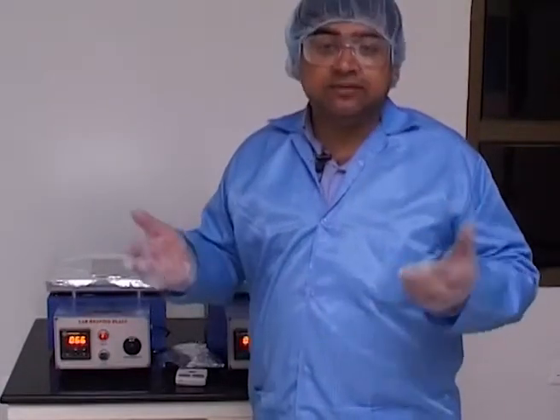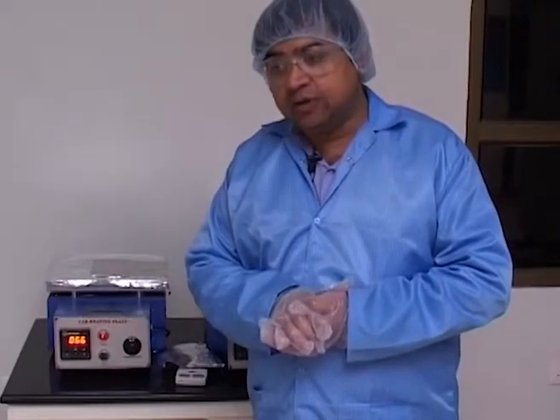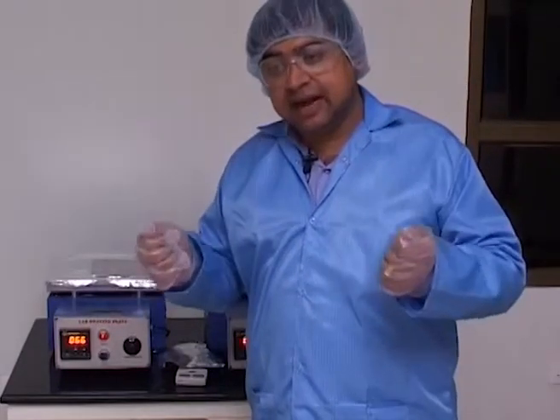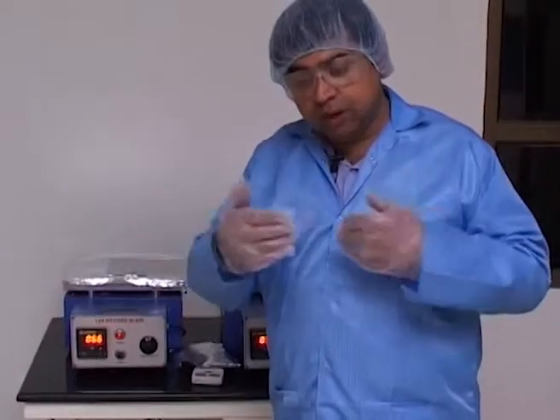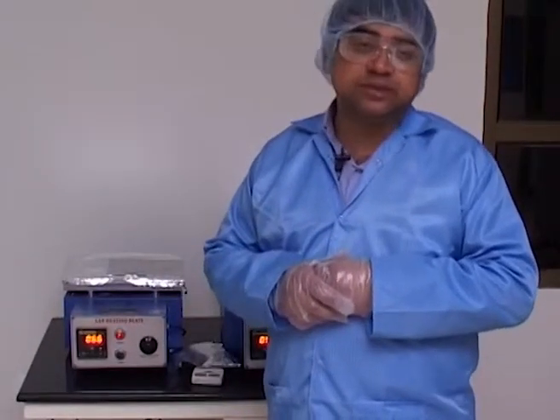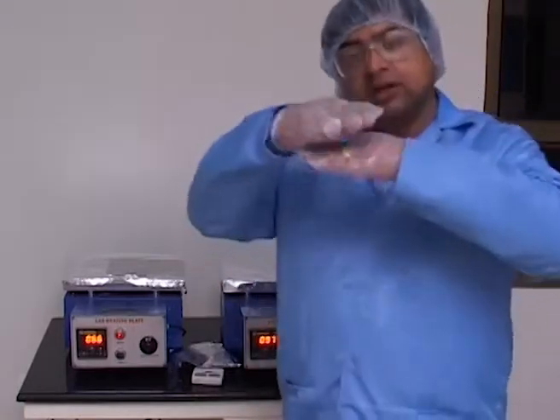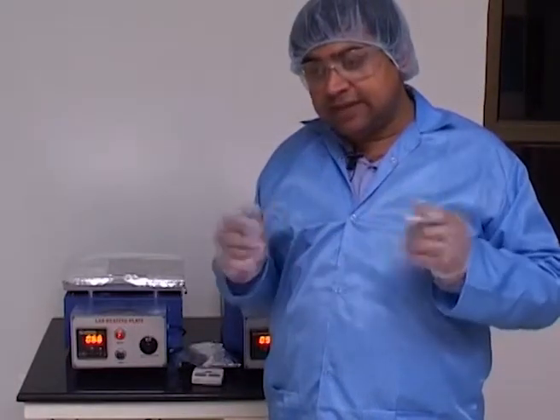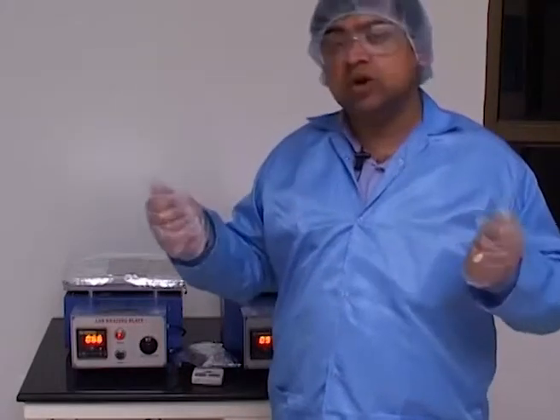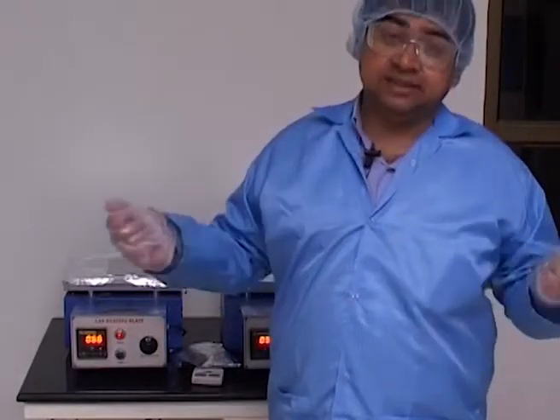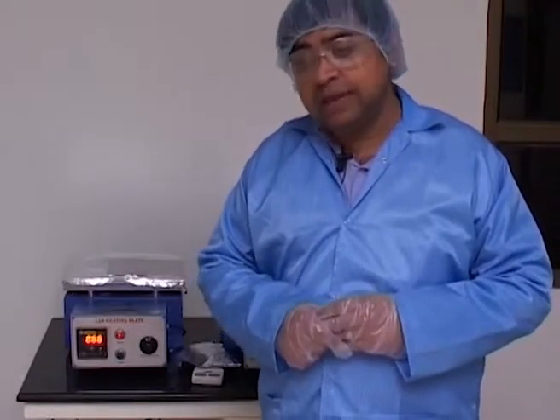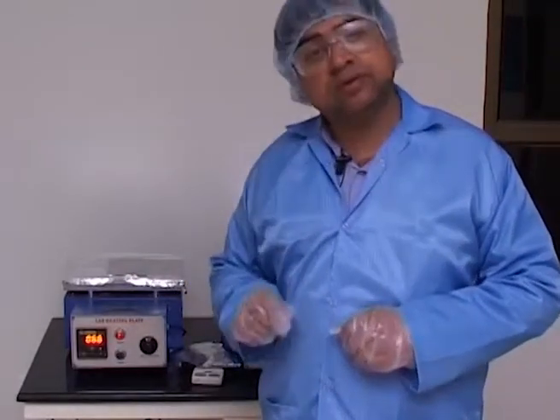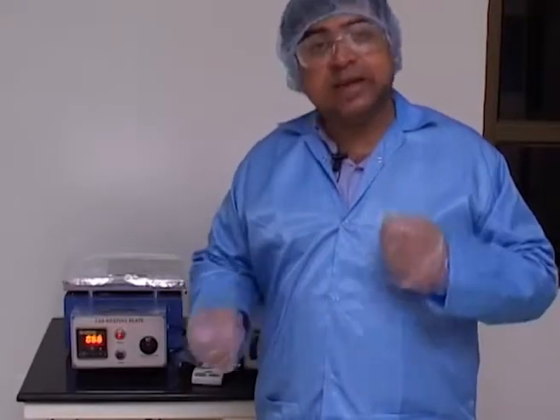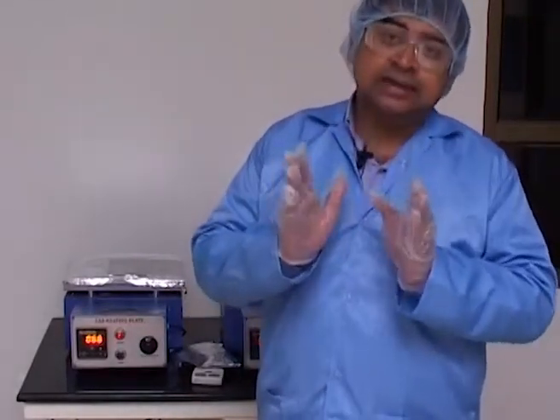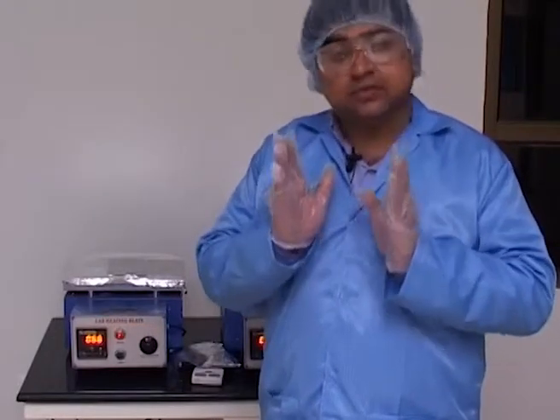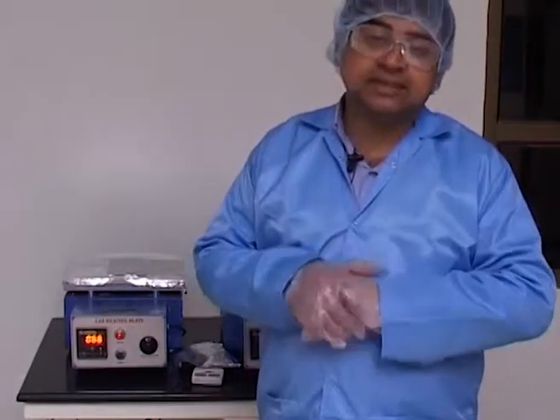And then we need to get rid of this solvent, because that would ensure that the resist film is stable, it is hard enough, it is kind of cross-linked, and before doing exposure this is very critical because the mask would sit on the top of the resist. Okay, and so if there is some undried or uncured portion, the resist is going to get damaged, and that is something that we do not want, because the surface of the micro features that would result will also be damaged by that. So we need to ascertain that the resist is fully cured before taking it to the next exposure step.